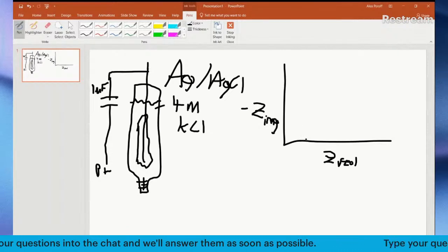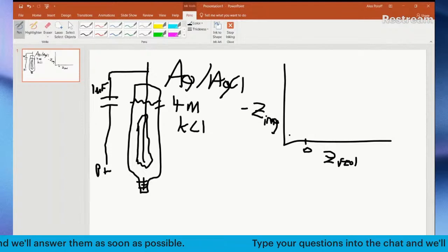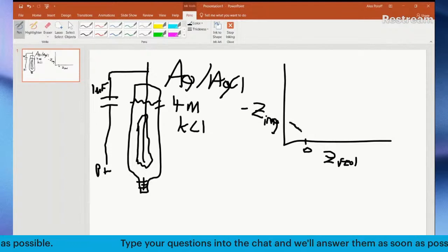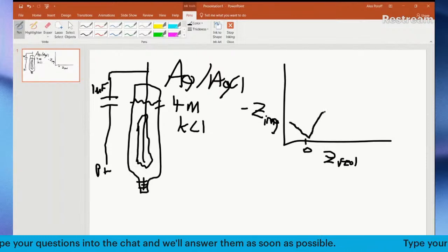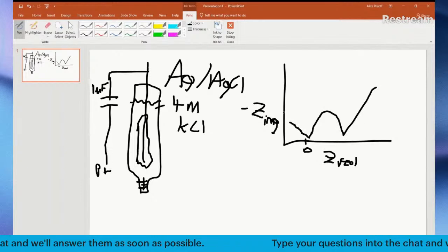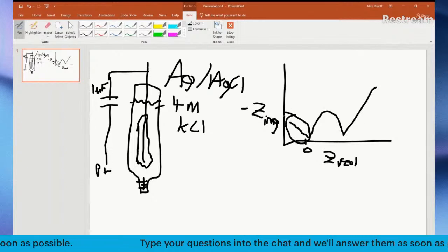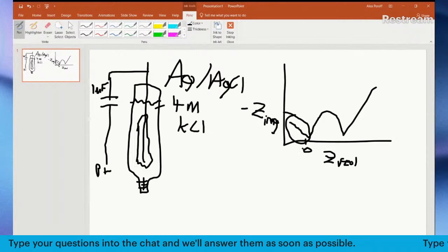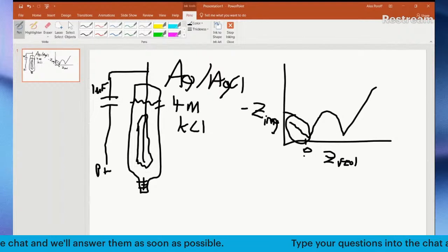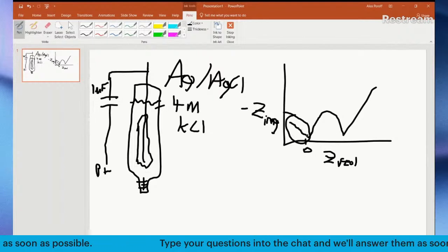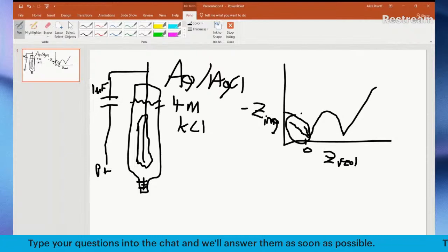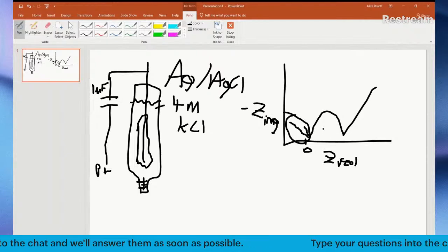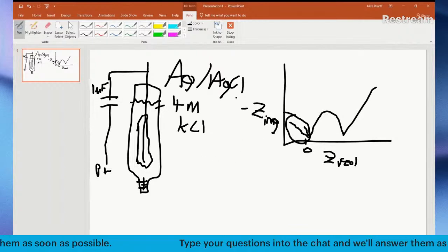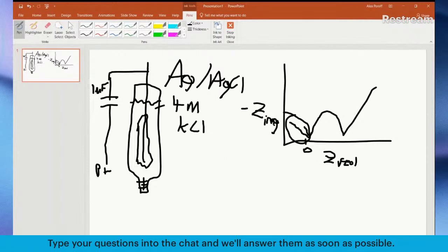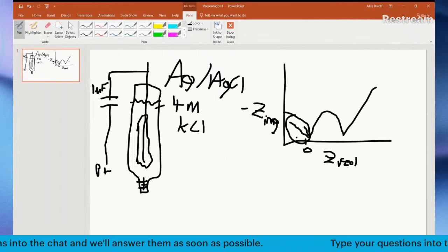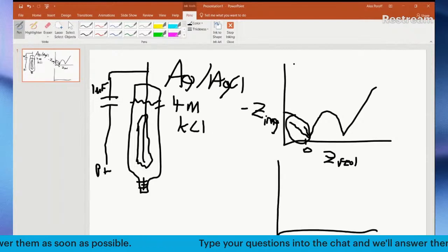When you have, let's just say for argument's sake, this is 0, you'll actually start to get some strange EIS signal that looks like this. You have these high frequency artifacts. Sometimes it can be negative real impedance, which also doesn't make sense. And in general, even if that wasn't there, having this little tail in the Nyquist plot is problematic. So what we do is we employ this reference electrode shunt.